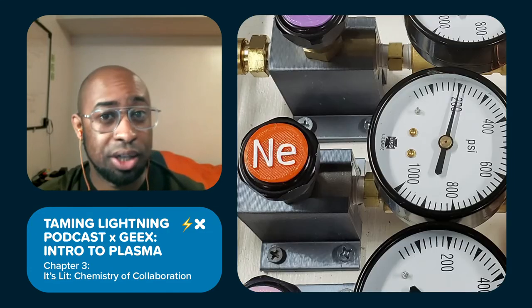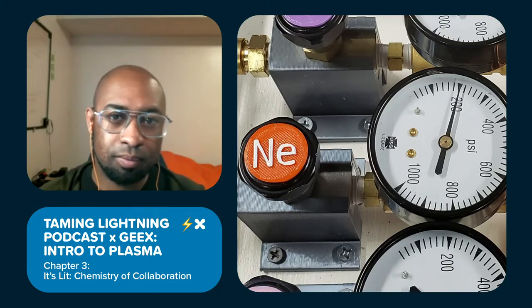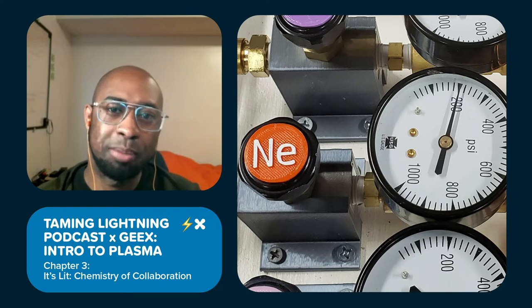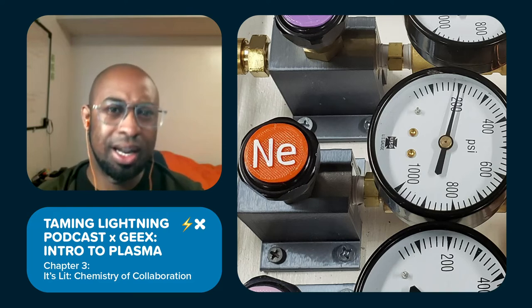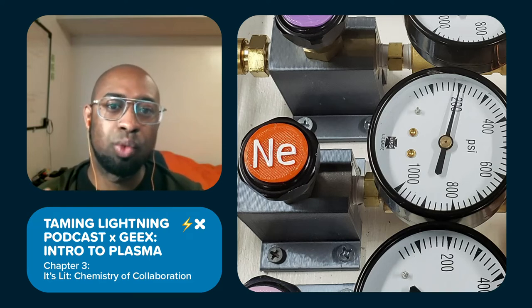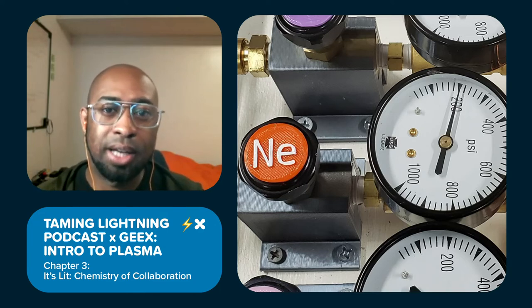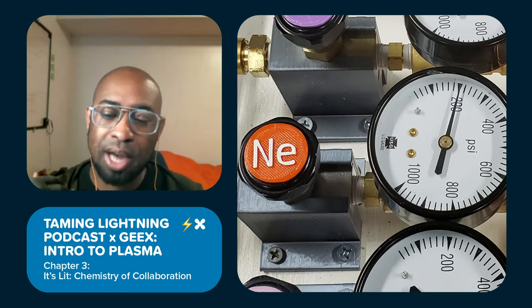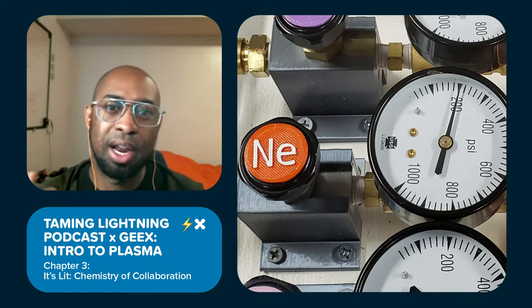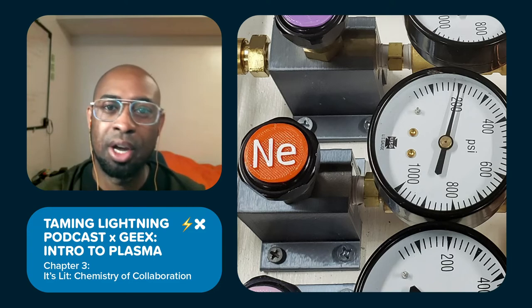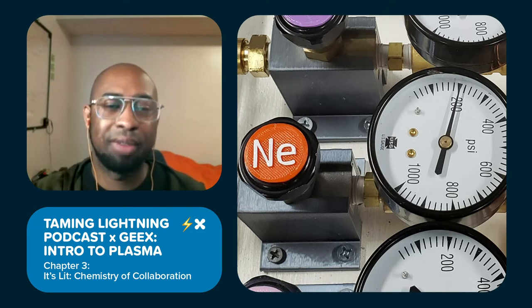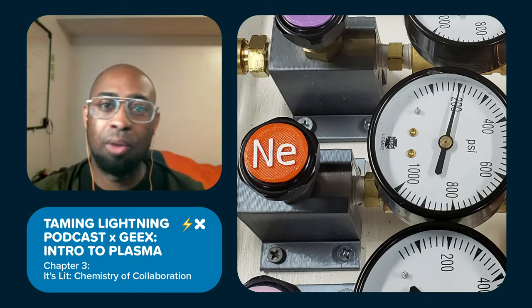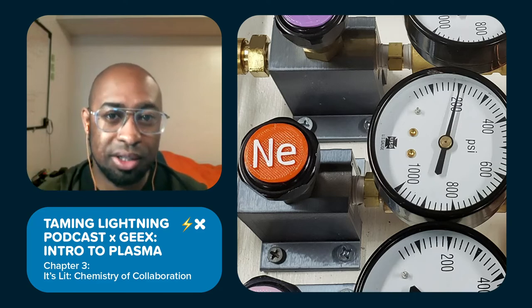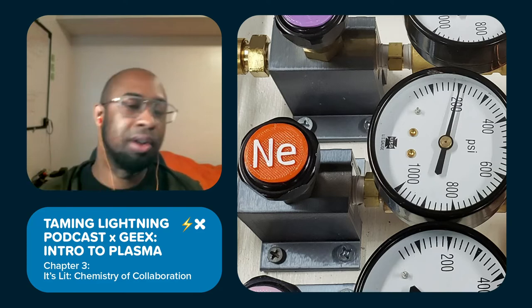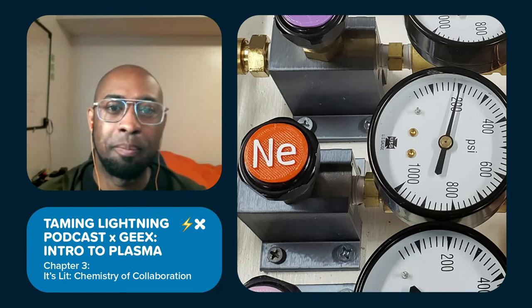Then the next step is flushing or rinsing the vessel. In this step, you're going to pick the cheapest and most dispensable gas, like neon, and fill the vessel up to 20 torr. You will then open the vacuum again to flush out. See, this fresh, clean, pure gas will interact with any residual molecules or particulate that may be inside the vessel from when the bakeout process happened or when you activated your electrode getters. And that will allow it to come right out, essentially rinsing your vessel out.